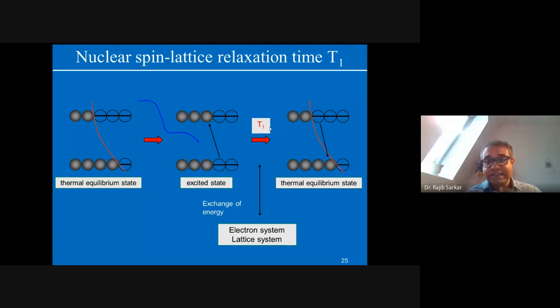The important thing is that T1 basically varies with how your nucleus interacts with its surroundings. Depending on the fluctuations or the dynamics of the electrons surrounding this nucleus, that information will be reflected in your spin lattice relaxation rate or the spin lattice relaxation time. By measuring these, you can get information about the dynamic nature of the electrons, and so you can get dynamic information about the whole solid you are measuring. So it is a really important piece of information.